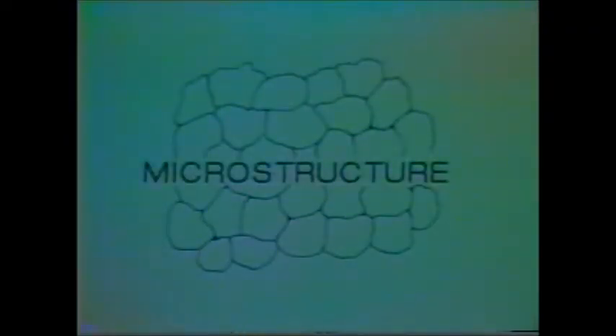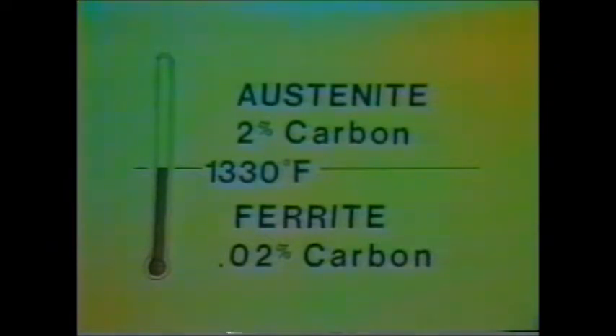Much can be discovered about the composition and structure of a steel by such microscopic viewing. The way steel is organized on this fine level is known as its microstructure. A steel's microstructure is strongly influenced by its chemistry and by the way it cools. At about 1330 degrees Fahrenheit and above, iron can dissolve nearly 2% of its weight in carbon. Below this point, it can hold only 0.02% of carbon by weight, only 1/100th as much as the hot phase.